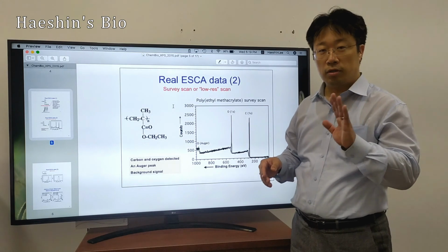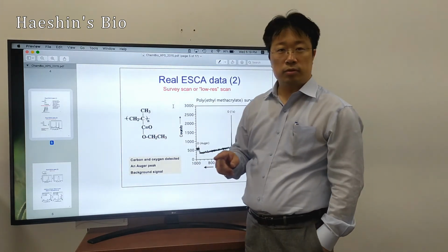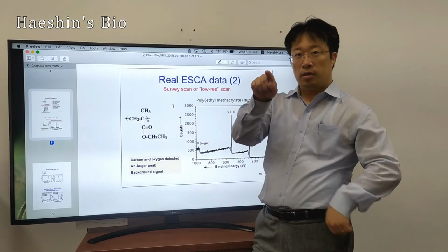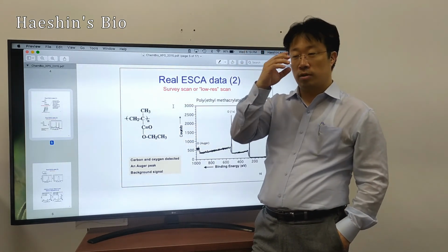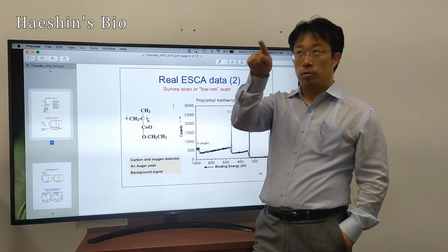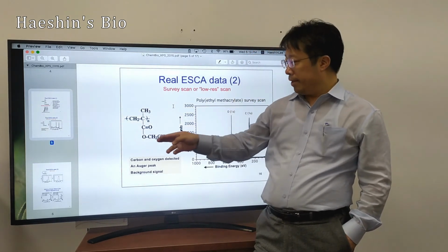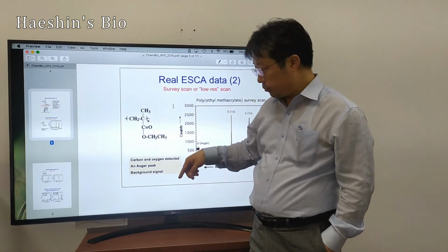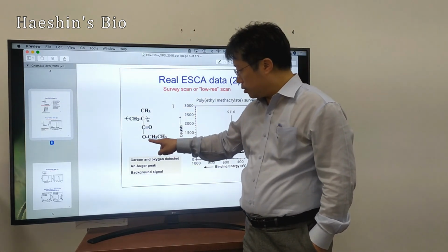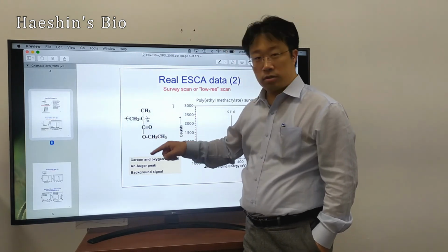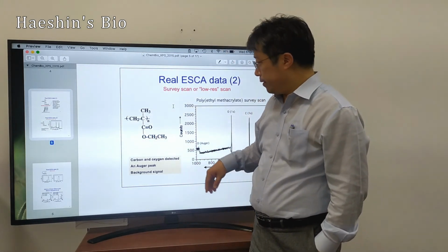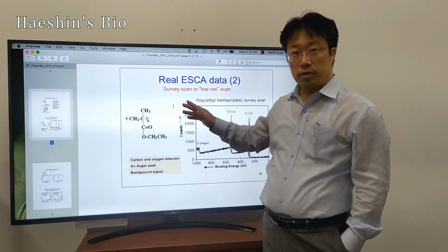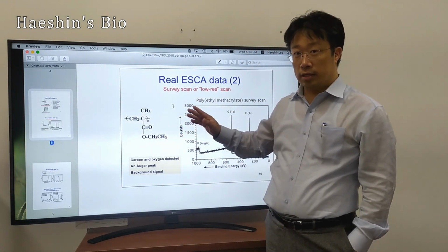So in XPS, you analyze what is right next to the carbon. In NMR, generally speaking, you have splitting and the three-bond rule, right? But in XPS, it's only one bonding rule, just the nearby atoms. Okay, so this is carbon, and this is oxygen and carbon, but the oxygen is dominant. Okay, so I will continue the XPS explanation in the next classes.